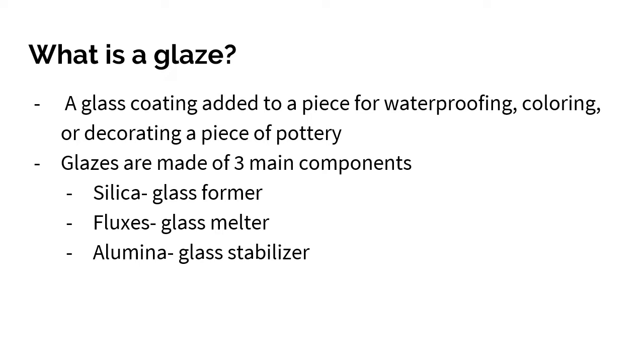So silica is a glass former. It's a combination of silicon and oxygen. Our fluxes are things that can help melt glass because silica melts at a very high temperature. And flux is Latin for the word flow. So it's helping that glass flow over the piece. And then alumina is our aluminum and oxygen combination, and it helps stabilize the glass.